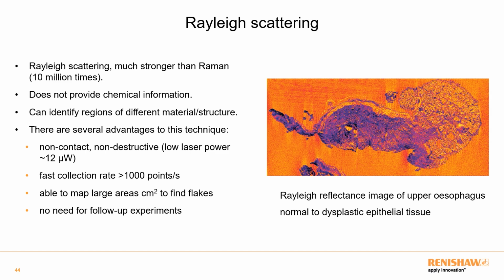You don't need very much laser power to do Rayleigh scattering because it's so strong, so it's inherently non-contact and non-destructive. On an inVia Contour, we're collecting data at rates greater than 1,000 points a second, and we're able to map very large areas to find flakes. So in this case, we can just do the maps very quickly. As a quick aside, this is a Rayleigh image of upper esophagus tissue, and here you can see from the Rayleigh image, we're able to get really good contrast on different features in the tissue.